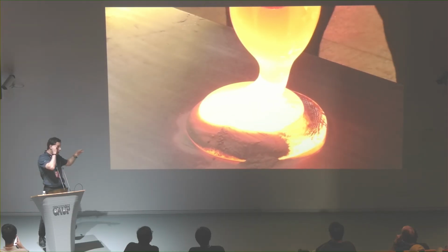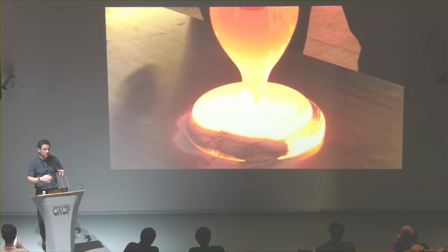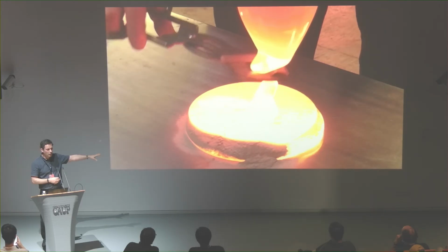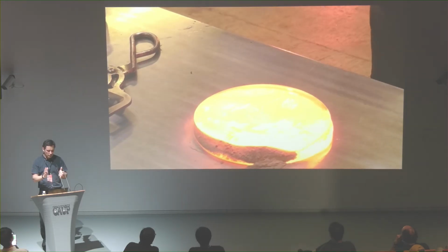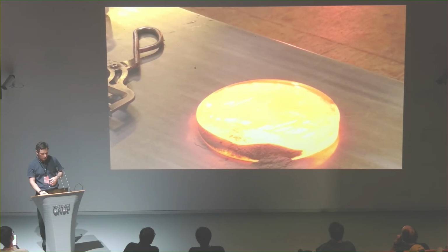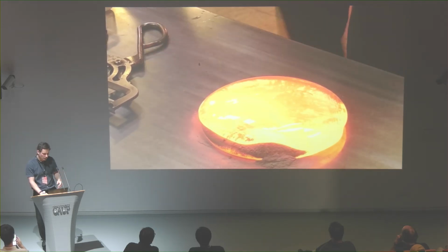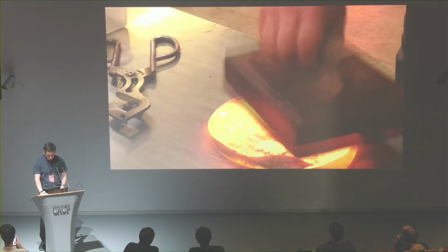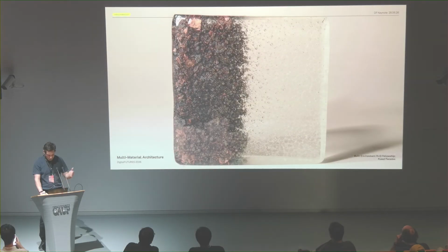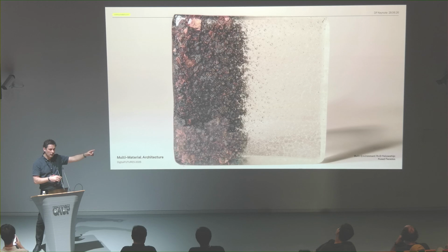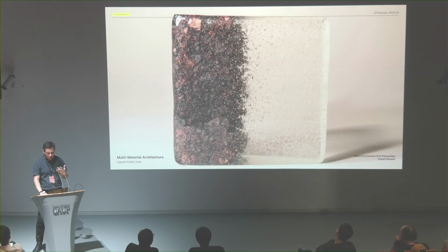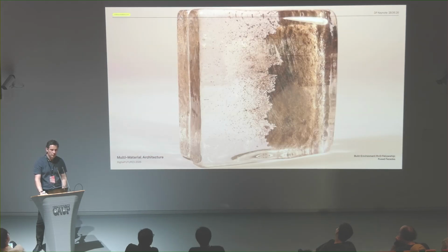So we did go for it, seeing could this ever be possible. We used aluminum powder, melting it in between molten glass, to see would that create a graded material. Of course it didn't, and this was the result. This was metal on the left, glass on the right. This was full of bubbles and trapped air. The metal didn't really fuse with the glass, but it was a very rudimentary, basic way for us to start to explore the idea.